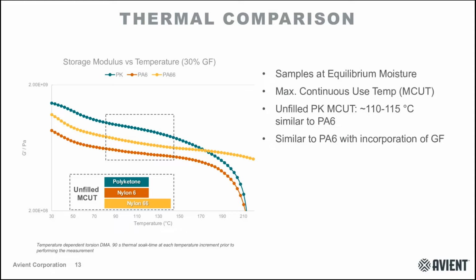And so when you're comparing polyketone to nylon 6 to nylon 6,6 in these graphs, what you see is that the material curves for nylon 6 and polyketone are very similar. They start to change their slope at around the same region, whereas nylon 6,6 has a relatively linear slope throughout the entire tested range, even above 210 degrees Celsius.